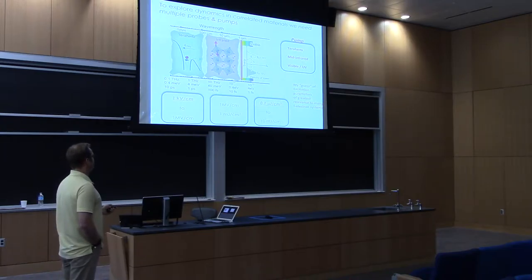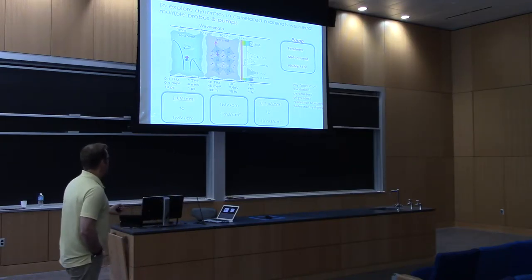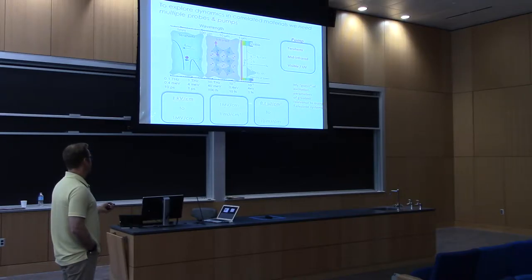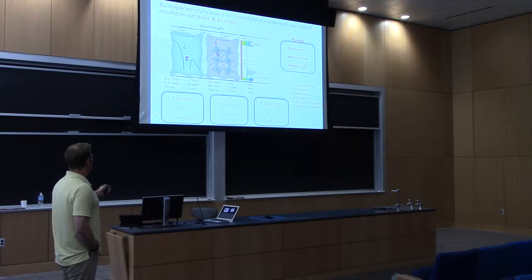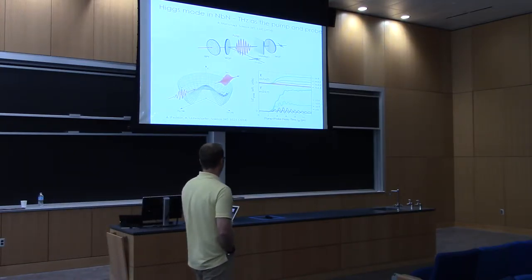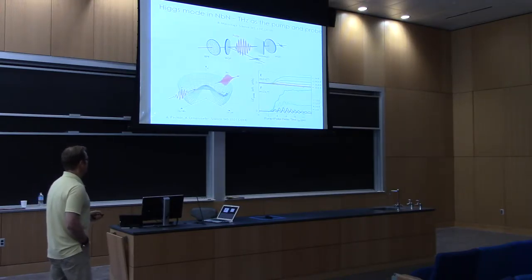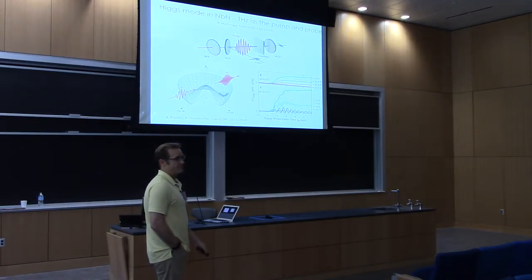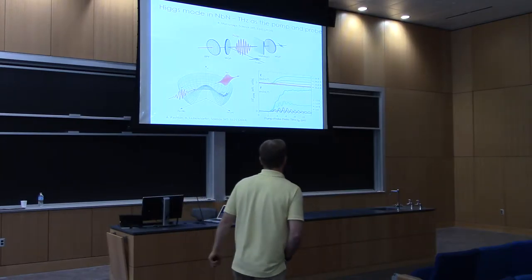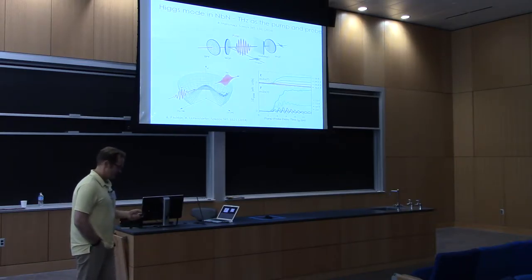So I'm going to give you a little bit more feel for what 0.1 microjoule per square centimeter or 10 millijoule per square centimeter means when you're doing optical pump. This is just a brief aside. My guess of excitation parameters of greatest relevance to many of these electron systems that we talked about this morning. On the optical side, this isn't really a guess. I know this because we do these experiments, but you want to be in the very low-fluence regime. And then as we move towards doing terahertz fields to drive these systems, I would guess you also want to be in kilovolt per centimeter range. And again, that brings us back to this idea we saw presented earlier in terms of the Higgs mode in Niobium Nitride, where you see coherent order parameter oscillations. This was done at very low field systems in kilovolts. So maybe this sort of idea will be relevant to some of these other materials at low temperatures.